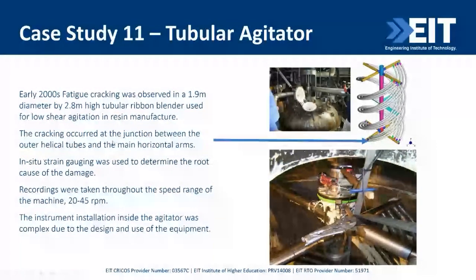Okay, the final case is this tubular agitator, a 20 to 45 RPM tubular agitator in a processing plant. Helical tubes welded to lateral arms for water cooling. An absolutely intense setup of telemetry and strain gauges. The outer helical arms on the lateral arms, they repaired 5 welds over 2 weeks, with more and more intensive welding and profiling, and the whole thing with no result.